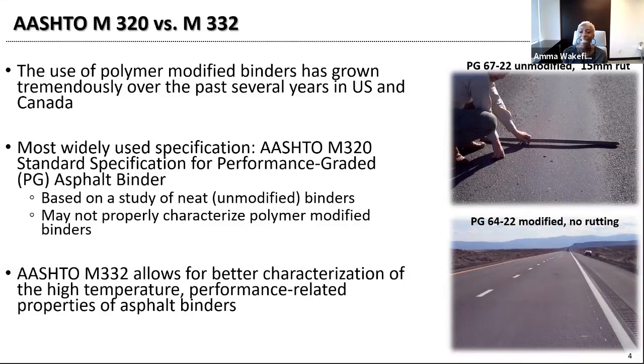The challenge is that for the AASHTO M320 specification for performance graded asphalt binder, the study that was done to come up with that specification only utilized neat, unmodified asphalt binders. So that's why it's difficult to characterize modified binders when you're using the PG system. Now, the photos on the slide show trial projects that were used to show what I'm talking about. The top picture shows a pavement section that was paved with PG 67-22. Keep in mind, the same aggregates were used. It was the same traffic conditions and environmental conditions. The only difference between these two trial sections is the asphalt binder type that was used.